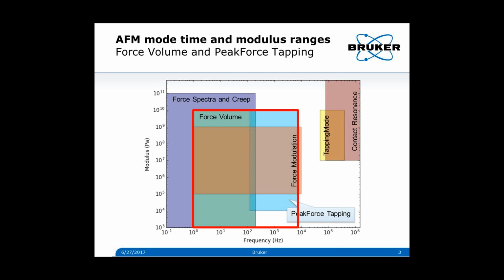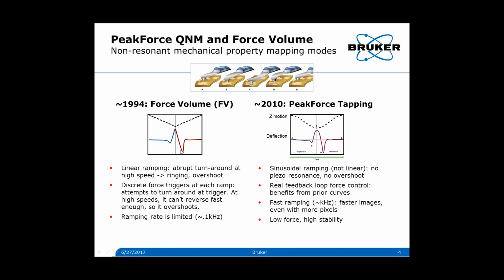Okay, so let's focus first on two of the non-resonant modes that are based on the same concept, force volume and peak force tapping, or as we often call it, peak force QNM. Force volume was developed in the mid-90s. It was one of the first, and it's still a great way to measure nanomechanical properties of samples. It works by ramping the tip up and down. This dashed line indicates the Z motion toward the surface until it hits a trigger value, which is a maximum allowed deflection, and then abruptly turning around and going back in the other direction. So it has linear ramping, but it has an abrupt turnaround.